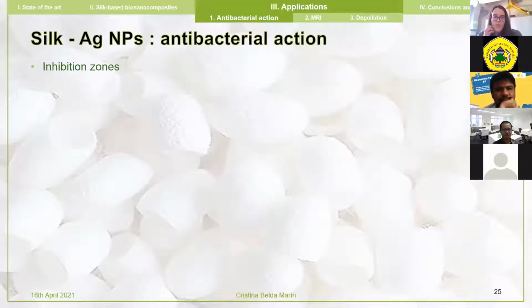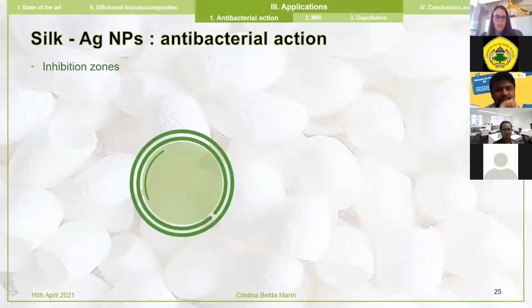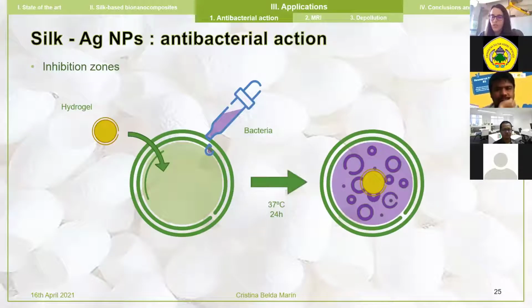So the first one is for silk containing silver nanoparticles. The main application of silver nanoparticles is, of course, antibacterial properties. And here we want to characterize whether our silk hydrogel has antibacterial properties or not. So what we do is place bacteria into a petri dish, place our hydrogel containing silver nanoparticles over the bacteria, and just see after 24 hours whether bacteria are able to grow or not.